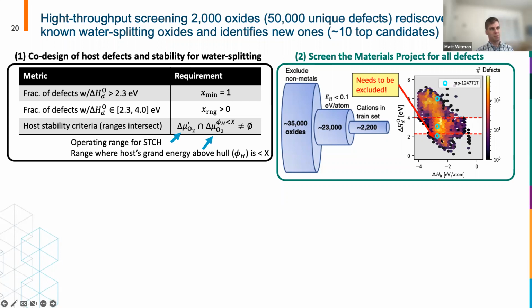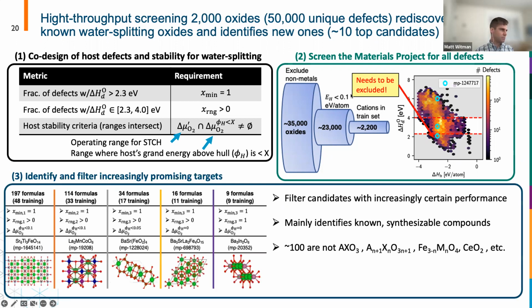And this is an example of one material where the range of vacancy formation enthalpies of oxygen is huge, and it's something that we need to discard because the lowest one is actually below this critical threshold. So we can apply various iterations or permutations of these down selection criteria to make the selection more or less stringent. But if you use the most stringent criteria, you get down to the order of 10 new materials that we'd want to test in the lab.